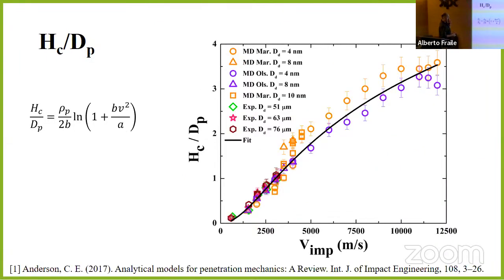And if we look at the depth of the crater, also divided by the diameter of the projectile, to put everything without units, again, we have a good fit and a good match between the experiments and the simulations. We have more points because we can go up to whatever we want in the simulation. In the experiment, they went up just to 4.5 kilometers per second. And again, the simulations are fitted with this model quite well. It's a model that has only the density of the projectile in this case, and two parameters here, and v is the velocity.